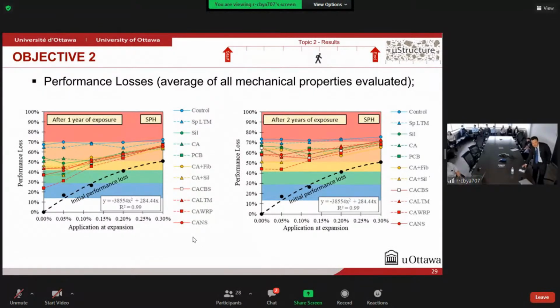And why did I ask you to save that information about the expansion? Because if we see here, applying the different surface treatments at 0.30% of expansion, after 1 year and 2 years of exposure, the overall performance loss between the different treatments is pretty much the same, even comparable with the control specimens. In other words, it indicates that the earlier we apply the different products, the better the results. Also, comparing the results from 1 year to 2 years highlights that maintenance is important to keep the performance loss of the concrete at lower levels.